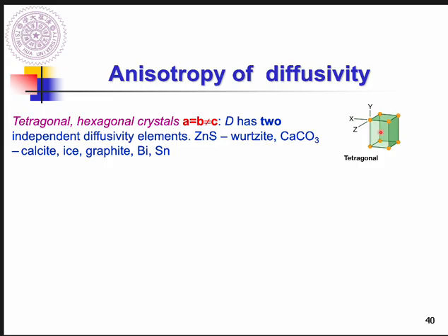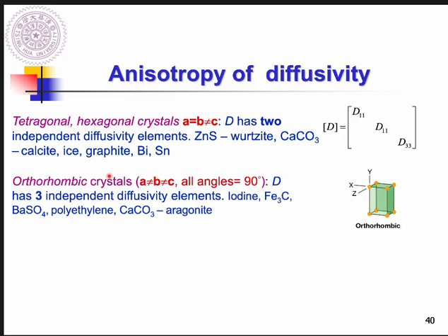diffusivity 会一样，C 会不一样，但他们都是90度，所以旁边这一堆都没有。So this belongs to anisotropic, an orthorhombic crystal, all angles equal to 90 degrees, but A not equal to B not equal to C. This implies that we have DA, DB, and DC. So we have D11, D22, and D33. All the axes are perpendicular to the others, so the rest of the diffusivities equal 0.